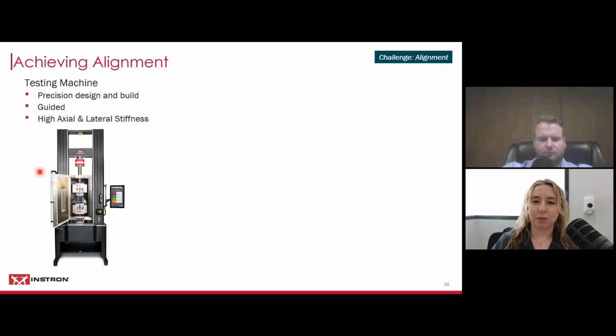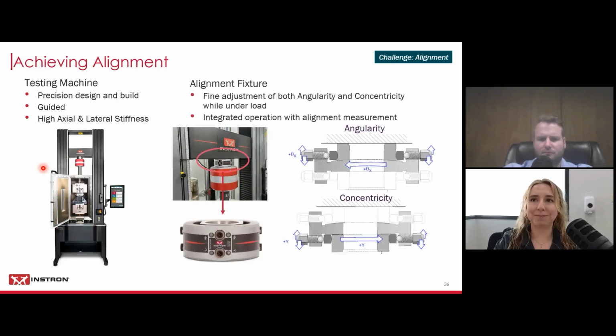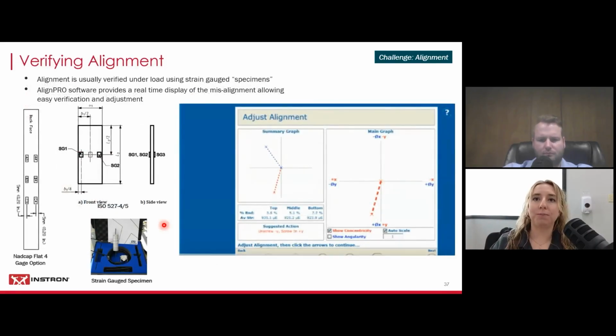And not only is that contributing to our alignment, but we want to make sure that the frame can actually handle the wear and tear of composite testing and those high energy breaks that we might be seeing over and over and over again. And then furthermore, we can add an alignment fixture to the load string. So here we can see our version of an alignment fixture called an Align Pro. It sits permanently in between the load cell and the crosshead. And there are 8 set screws on the Align Pro, and you can adjust these to adjust for your angularity and your concentricity. And in the next slide, we actually show the effects of adjusting those.